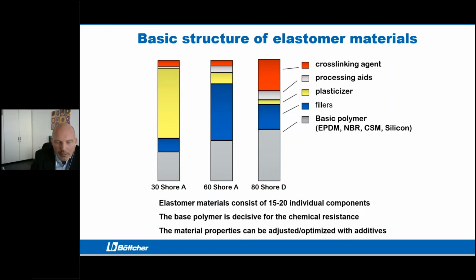The basic polymer like EPDM or NBR is mainly responsible for the chemical resistance. This means if we have swelling or shrinkage, or if it's stable, and we can do also some additives to adjust the different properties. Here is a sample for a different hardness, which can be, for example, 30 Shore A, which is quite soft, then 60 Shore A or 80 Shore D, which means this is very hard material. And depending on the recipe, we have different properties of the material.